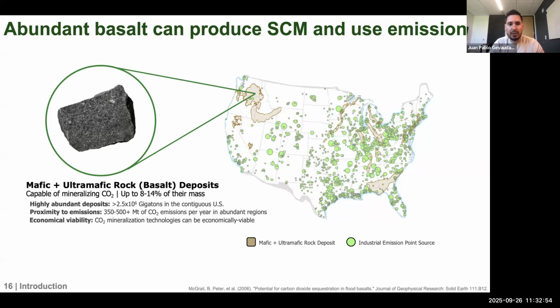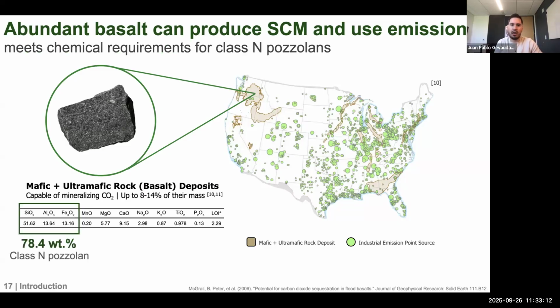Well, one of the things that is really attractive here is that beyond just the abundance of basalt, we also have that proximity, but also we have about 8 to 14% of their mass being calcium and magnesium. So here is XRF data from our lab. And what we can see is that we have around 14% by weight of that magnesium and calcium oxide, which we can use to mineralize CO2. But also we have about 78.4% of silica, alumina, and iron oxides, which is really attractive if we're thinking about this material as an SCM, perhaps a class N pozzolan. So more on this later, but this is very exciting because we can see the potential for basalt to meet both needs.